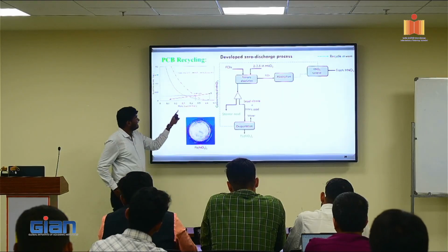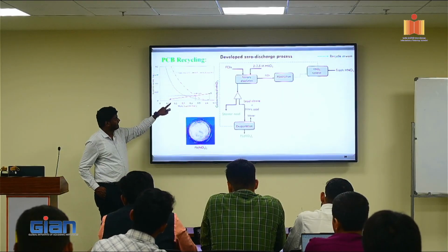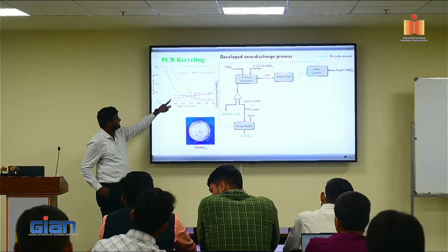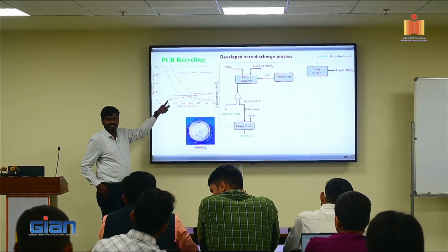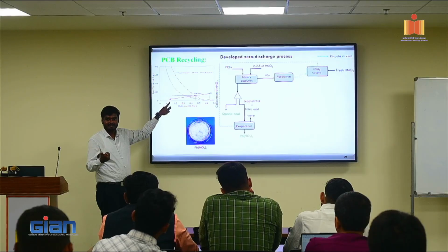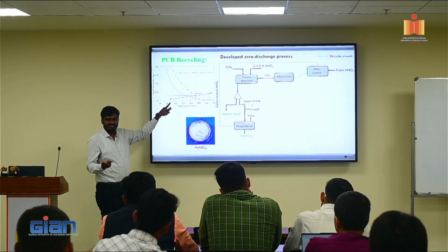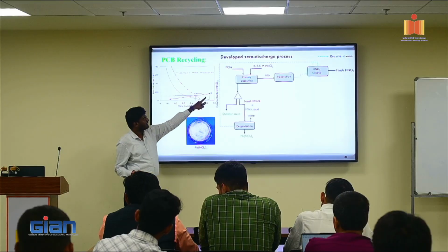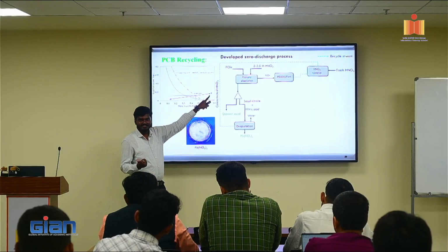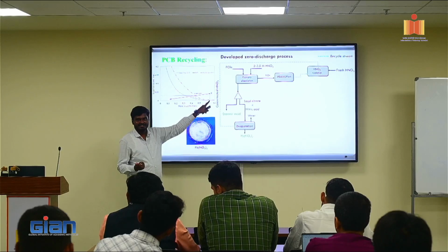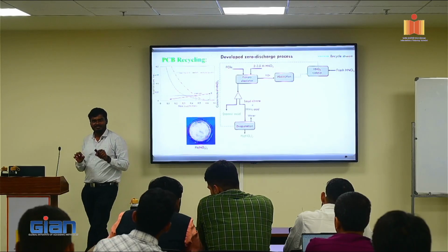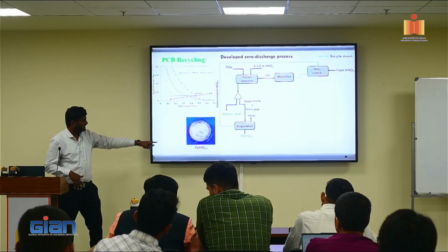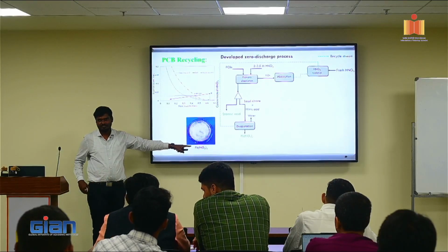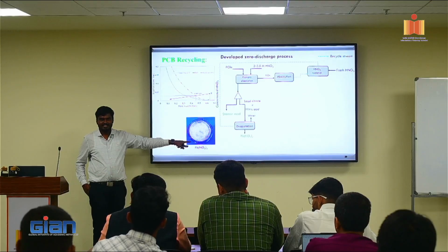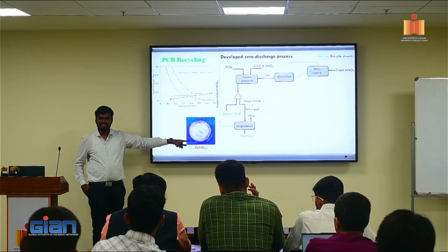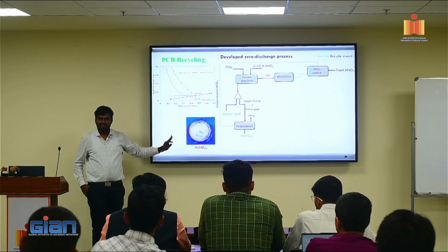So initially we are at this point, where the acid weight fraction is here and lead nitrate is here. Typically when you separate water, acid concentration will increase and lead nitrate concentration will increase. So we are supposed to come to this point, but lead nitrate is insoluble. Typically we fall here. So there won't be any lead nitrate in the solution, it is precipitated out. That is these lead nitrate crystals. We analyzed them and they were highly pure, more than 99.5% purity. So we got one more product.